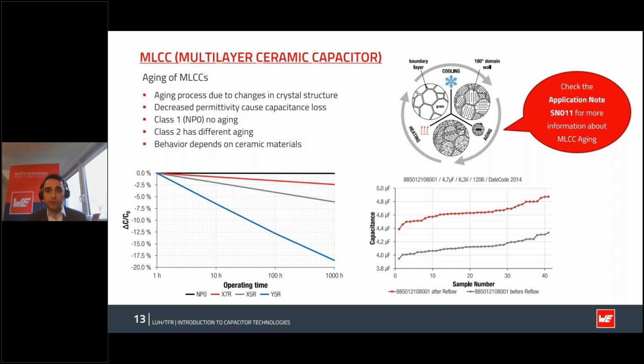And this aging is per decade. So if you would calculate for 10,000 hours, you can double it. For 100,000 hours, you can triple it, and so on. This applies to all ceramics here. Then in gray, you see the X5R ceramic, which has a stronger DC bias effect. Here you lose usually about 4 to 6% per 1,000 hours of the capacitance.